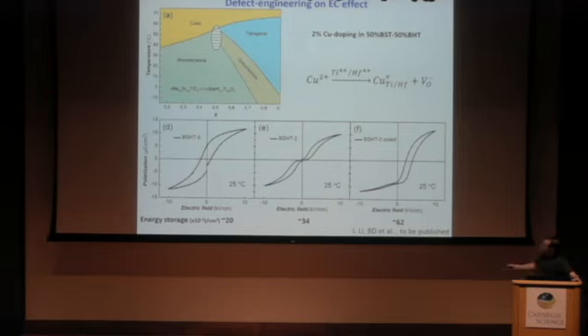And because of this, you see, we start with the non-doped system, which is normal ferroelectric. And once you dope, we have this pinched hysteresis loop, as Tadei showed yesterday. And if you apply a given poling condition, you can even strongly change the hysteresis loop. This is very interesting because you can now think in that way. What we need is disorder. And of course, the way of having disorder is to have a P max much bigger than P remanent. It means that you have a lot of entropy in your system.